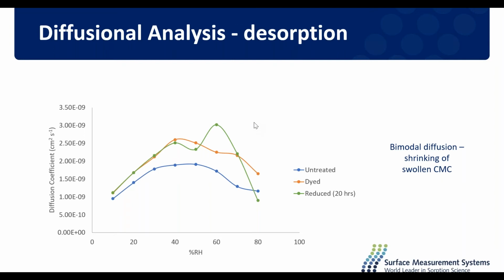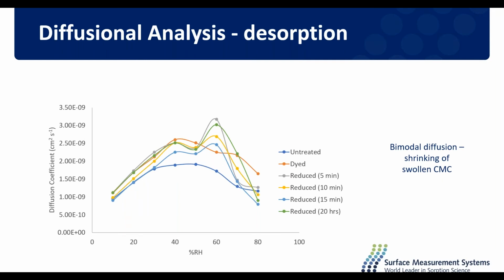So we believe that this additional peak of fast diffusion occurring at high relative humidities is related to the more effective relaxation of our hair fibres as they begin to shrink. And we can see from our other reduced hair samples, they show a very similar behaviour.